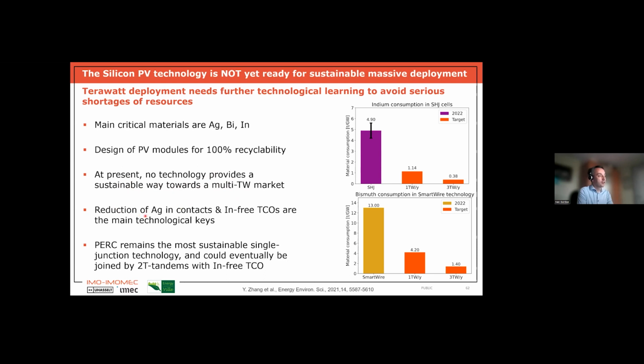Especially we have to further reduce the amount of silver that we are using and also the amount of indium. So we should really try to get indium-free TCOs working properly. This is very important for the tandem concepts. And so although the industry predicts that the PERC solar cells will at some point be replaced in production by TOPCon and/or silicon heterojunction, it's possible that we will have to stay producing PERC for a much longer time because PERC at the moment is the most sustainable technology that we have. So from a sustainable point of view, PERC is actually doing better than the others.